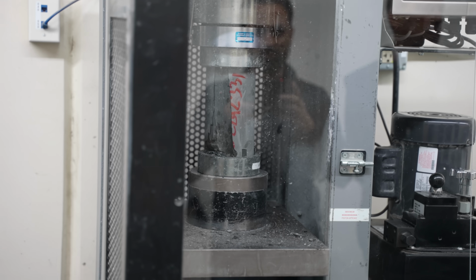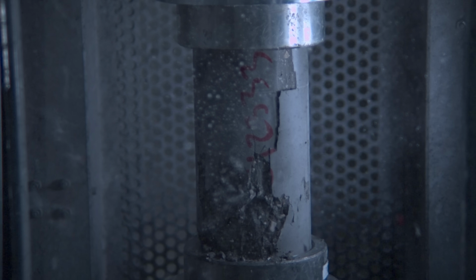Cement is the most expensive part of concrete, so if you can get away with reducing it down to 30% in the mix and still get the same strength characteristics, well then you should definitely do that. The other thing that was interesting was pure cement seemed to flake and chip more as it was loaded. So it seemed like adding the aggregate actually helped the sample cohere and stay together even under all that load.